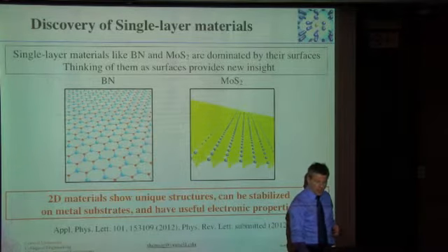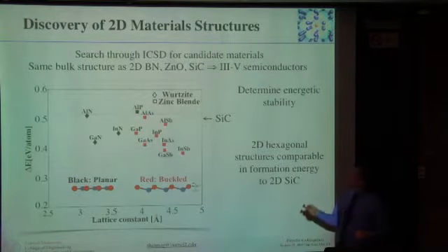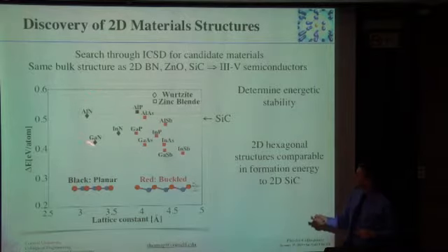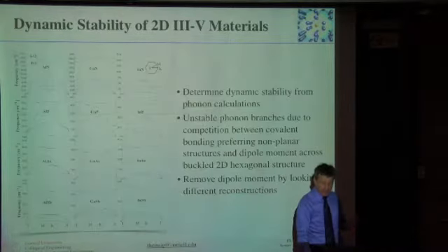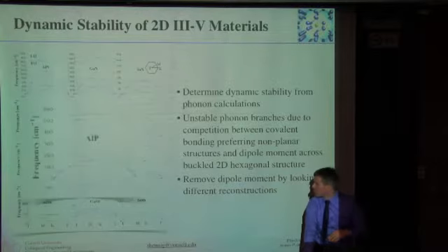carbon atoms. And so we data mine looking at the crystal structure database, and then we find there's a lot of III-V compounds, and they have relatively reasonable formation energies in the 2D form relative to their bulk form, similar to silicon carbide. Silicon carbide has been made, so we think some of these may be able to be made. We look at their dynamic stability by doing phonon spectral calculation. Let me just skip through some of this.